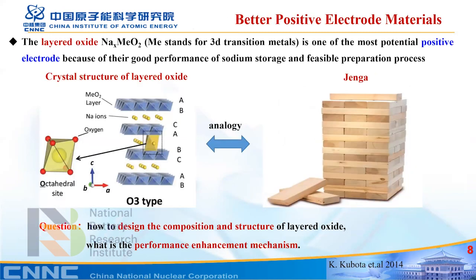So let's take a look at the structure of the battery. One of the most promising positive electrode materials is the layered oxide. You can see it layer by layer, because of its good performance and easy preparation process. Here we show the crystal structure of the layered oxide. You can see here we have sodium. The yellow color is sodium ions, which are sandwiched between the transition metal layers, which we label as TM, to form a layered structure along the Z-axis. For the crystal structure, C is in this direction.